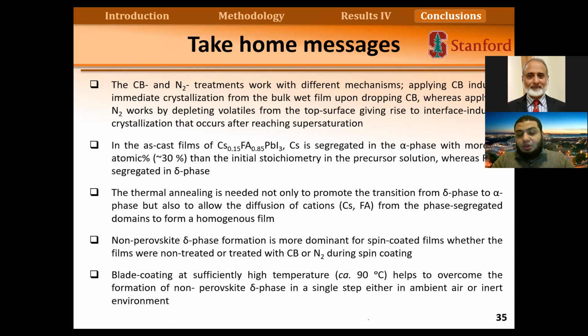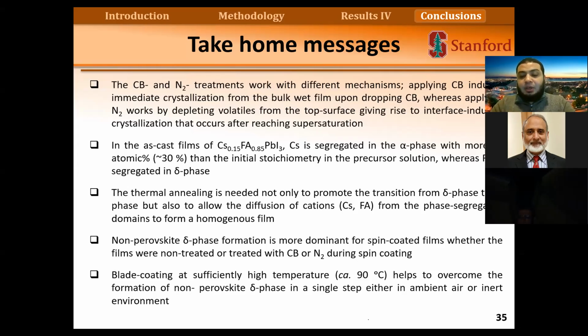And the take-home message from this: we found that the two treatments that we apply, the chlorobenzene treatment or the nitrogen drying treatment, both work with different mechanisms, but we end up with phase-segregated domains in which more of the cesium goes into the alpha phase and the FA goes to the delta phase. Annealing is needed for both cases, in which the thermal annealing helps to form a homogeneous film, helping to dissociate the delta phase and diffuse the delta phase compounds into the alpha phase, forming a uniform film with cesium and FA with appropriate stoichiometry. For spin coating at room temperature, we usually end up with a film that has amorphous, delta phase and alpha phase, which requires heating. But if we use blade coating, alternatively, we can form a perovskite in one step.